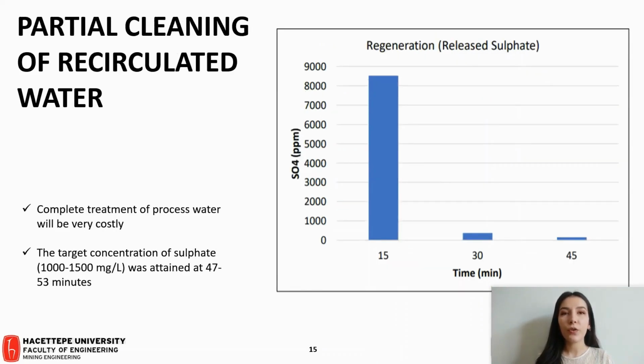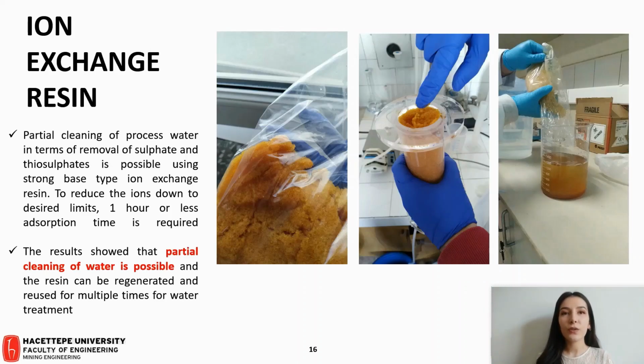Complete treatment of processed water will be very costly. Therefore, in this project, partial cleaning of recirculated water down to a sulfate concentration of 1000 to 1500 mg per liter in the plant was investigated. It was found that using a strong base type ion exchange resin in a column system to reduce the harmful ions in water to acceptable levels was possible.